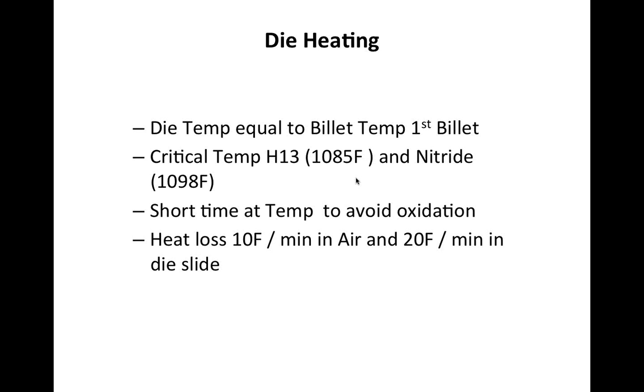We also know that the longer the die is left at temperature, the more oxidation we get on the bearing, which causes deterioration in surface quality of your profile. So we would like to limit the time the die is at temperature to as short as possible. In best practices today, it's 8 hours, which means that the die can only stay in a die oven for 8 hours, after which time it comes out of the oven, goes back to the die shop for polishing, and then comes back out for extrusion again.